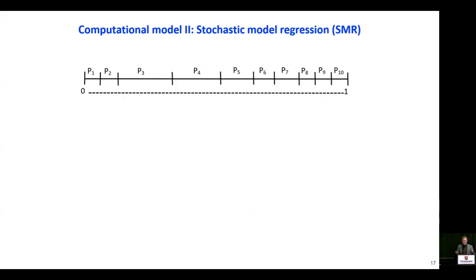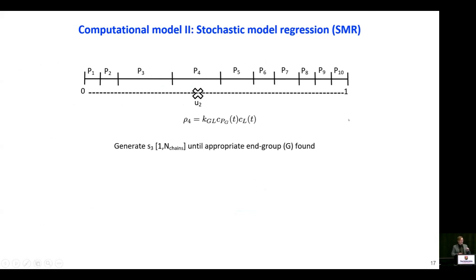Here's kind of a cartoon of this. We have a number line that is delineated by the number of options that can happen. We can add, say, a glycolide to a lactide chain end, et cetera. We generate a random number. This selects which reaction occurs. In this case, it's adding a lactide to a glycolide chain end. We find a polymer in an array type data structure that we can apply this to.